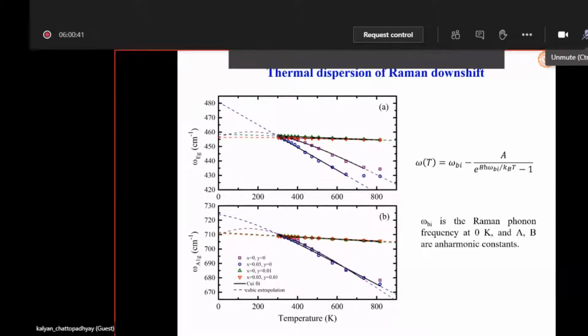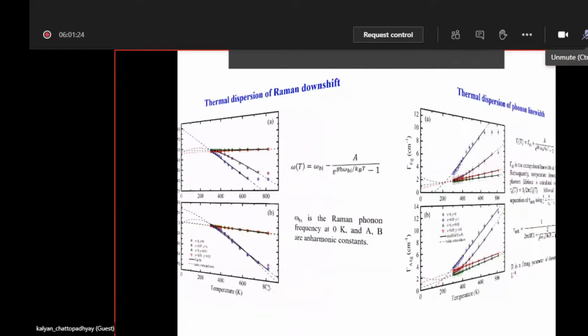But the main feature I just want to tell you is that you have seen the spectra, how with temperature the peak positions, that is omega Eg and omega A1G, shift. Then you can fit this variation of omega Eg and omega A1G with T, and you get such plots. Then we can extrapolate to find the value of omega Eg at 0 Kelvin, because that will be required for some calculation, and you can do that for both the Eg mode and A1G mode. So that has been done.